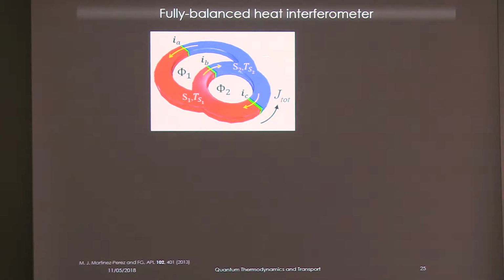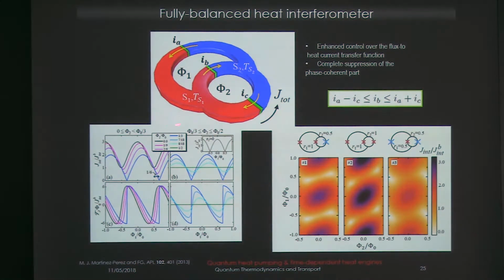So one trick, if one can think of a system that is by construction not very ideal in some sense, is to replace one of the junctions with a second DC SQUID. It can be demonstrated that there is a way to always have a perfect balancing of the system, in any case, if, for instance, the resistance of one junction satisfies a relation with the critical current flowing in one junction, comprised between the difference and the sum of the two. So in this case, it's always possible to have the full compensation, so the suppression of the interference part. So in our case, the suppression to zero of the phase-dependent part.